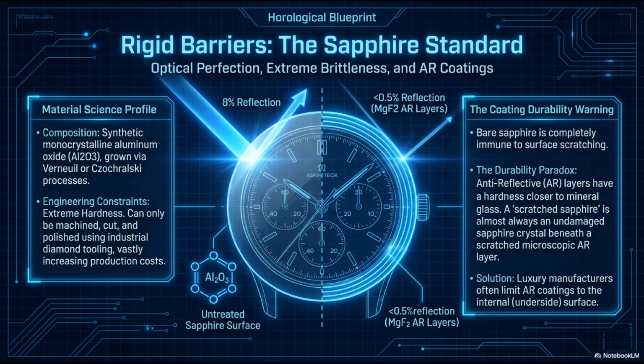Bare sapphire is completely immune to standard surface scratching. However, the AR coating layers are much softer, closer to mineral glass in hardness. When a client complains that their sapphire crystal is scratched, 99% of the time, the sapphire is perfectly intact. It is the microscopic AR layer that has been gouged. To solve this paradox, many luxury manufacturers now refuse to coat the top of the crystal, limiting AR coating strictly to the internal underside surface where they cannot be touched.